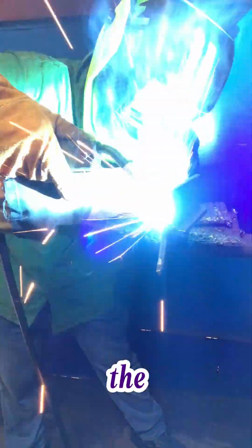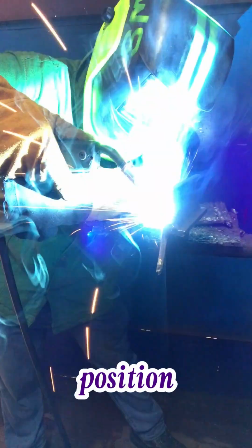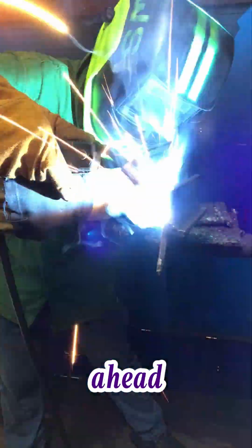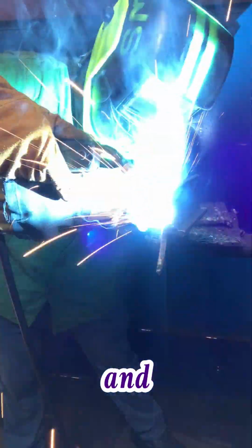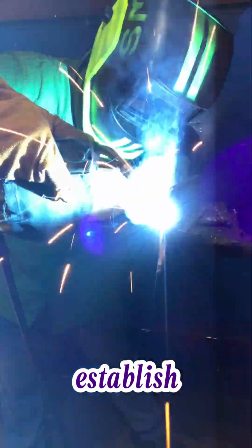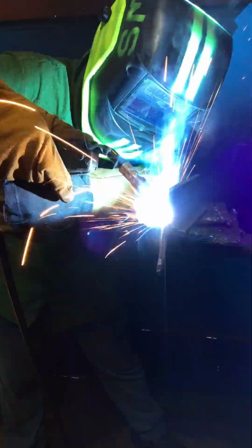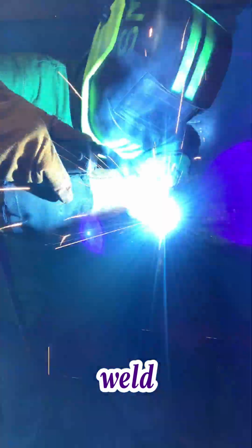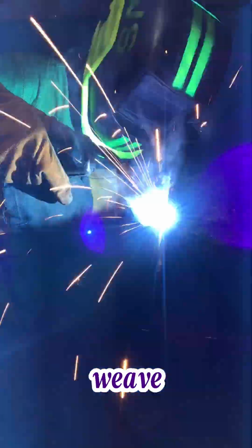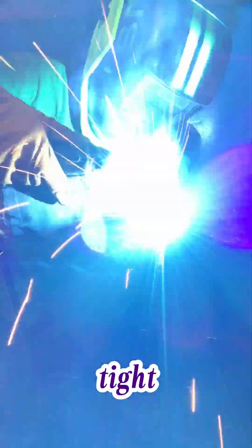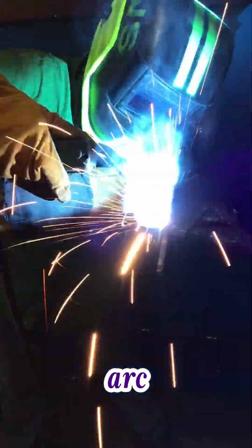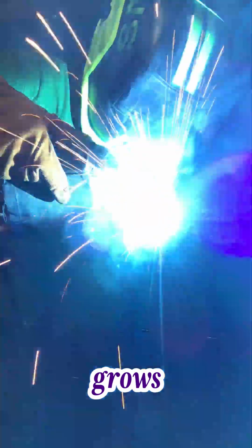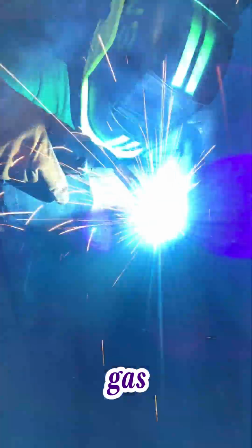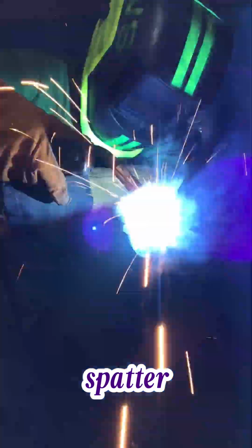Now let's strike the arc and run the bead. Position the wire 1/8 inch ahead of the joint, pull the trigger, and pause for half a second to establish the molten puddle at the root. Watch the trailing edge of the weld pool. Maintain a steady travel speed. You don't need a heavy weave. A straight stringer bead or a tight, subtle C motion is best for beginners. Keep your arc short. If your wire stick out grows past 1/2 inch, shielding gas coverage weakens, causing spatter and porosity.